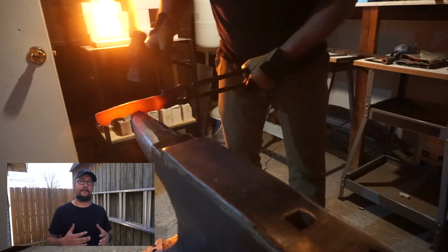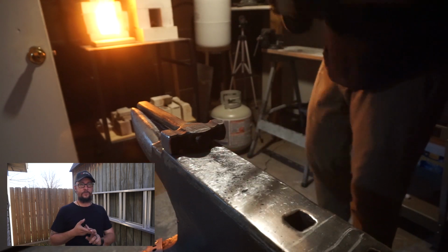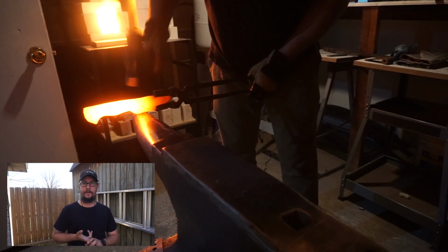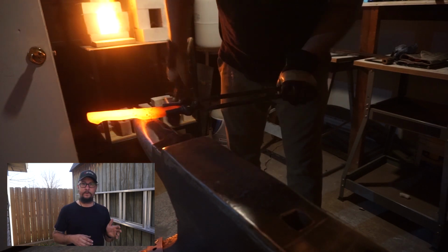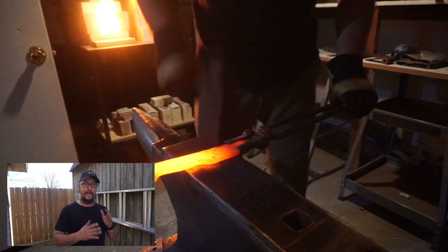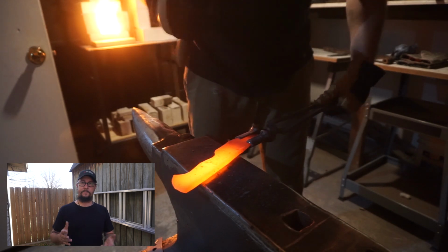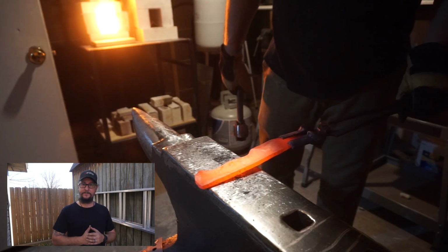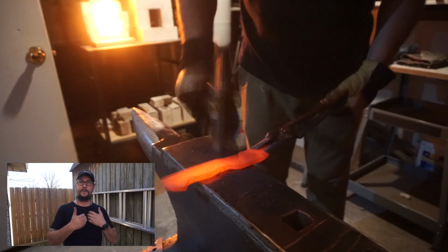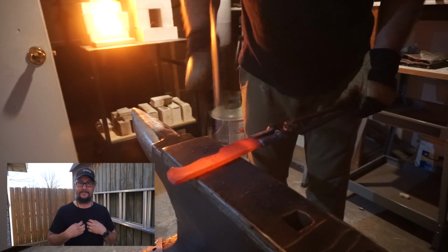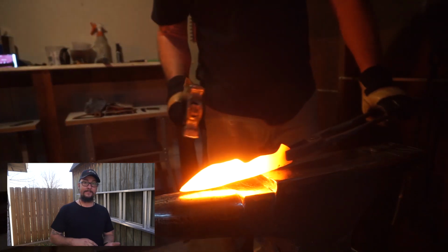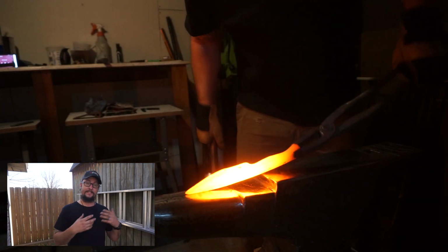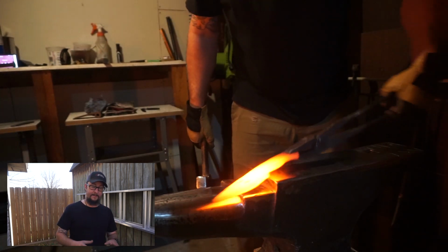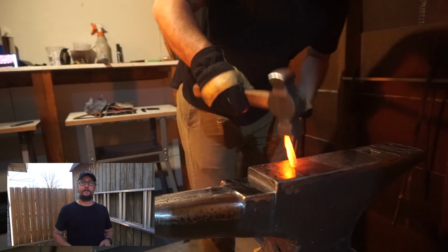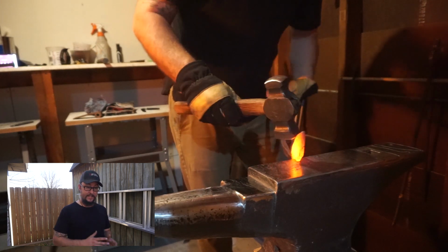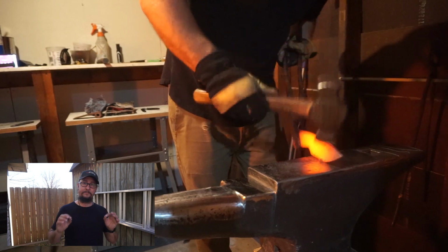I personally don't like to make my knives as soft as a 2-hour 375 degree cycle would be. So I fluctuate between 1 hour and an hour and 15 minutes at 375 degrees. I get a nice straw finish for that, and part of that might be because of my particular little toaster oven that I use. That is the length of time that I know that I need to get the edge retention that I want. And different steels are going to have different tempering cycles that are suggested for them. So that's another thing that goes into whenever you think, hey, I'm going to use 1080 and I'm going to work with that. I suggest for that first year, if you're just getting into knife making, that you only make knives out of 1080.